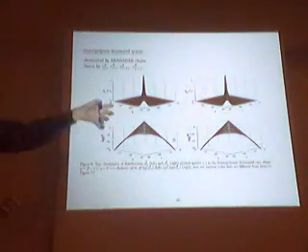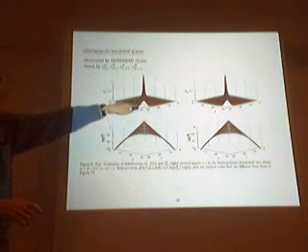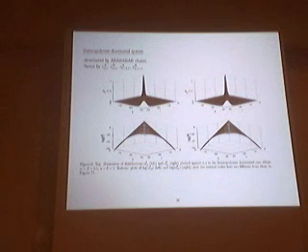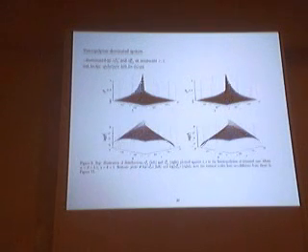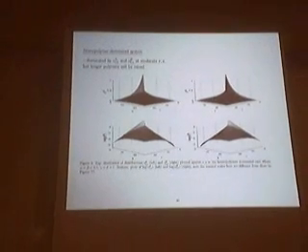So then you get a similar sort of normal distribution, but this is very tightly peaked around R equals S. And the more interesting one is the reverse case, where you tend not to get AB polymers, but you do get lots where the rate of forming homopolymers is very high, KAA and KBB dominate KBA and KAB.